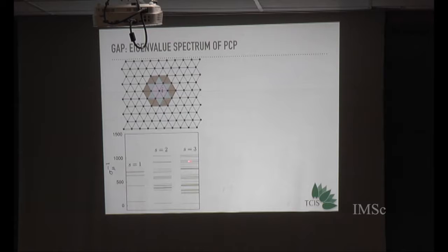Okay? And if I increase the coarse graining volume, what happens is that all the upper energy levels get filled, but this gap remains. So there is a big difference between really the most probable non-affine motion, which is represented by the lowest eigenvalue, and all the rest. Okay. So let us look at what contributes to this lowest eigenvalue, this highest eigenvalue. And these are the eigenvectors associated. So it's a degenerate. There are 2 degenerate eigenvectors.